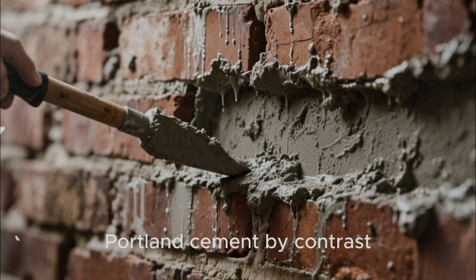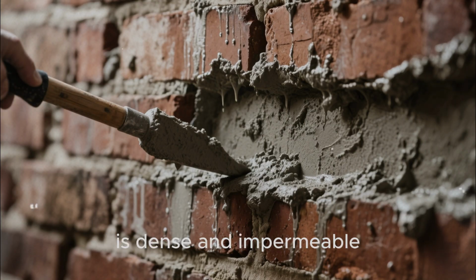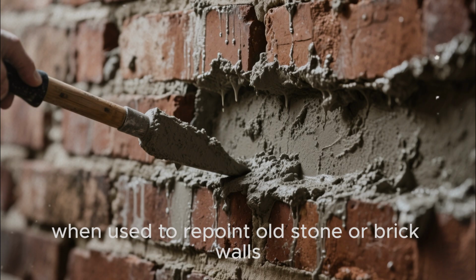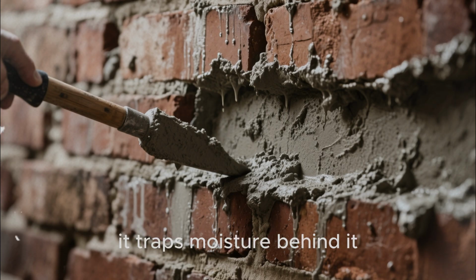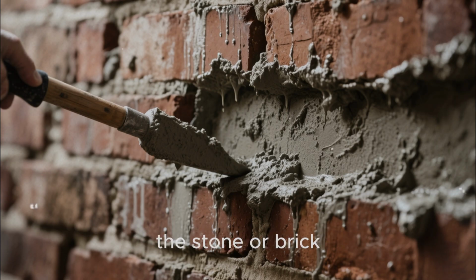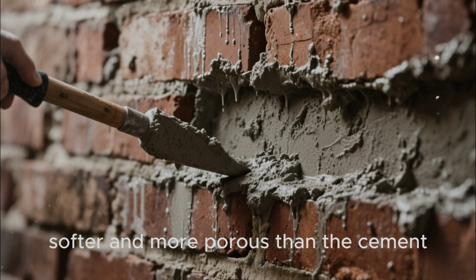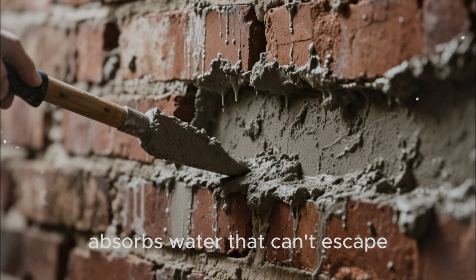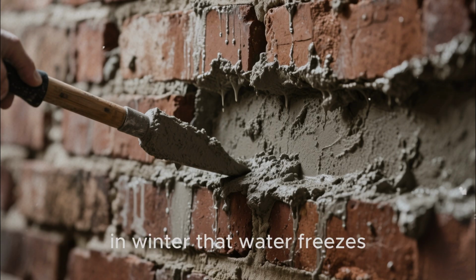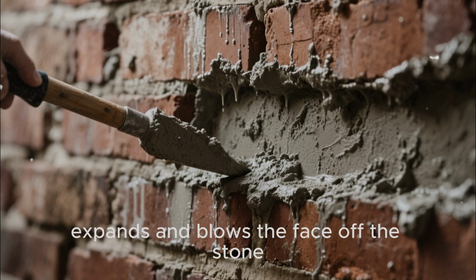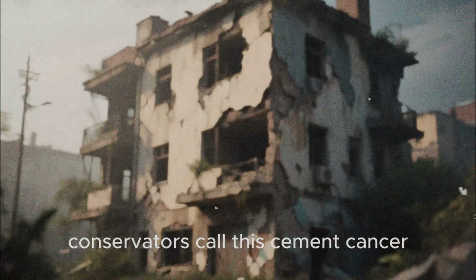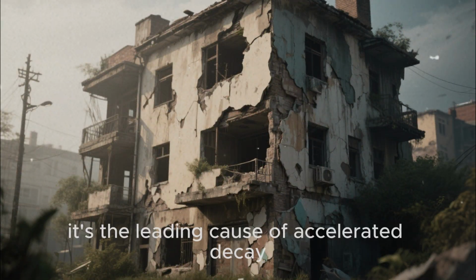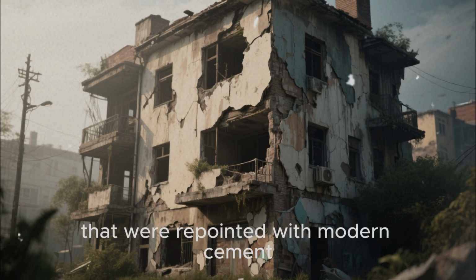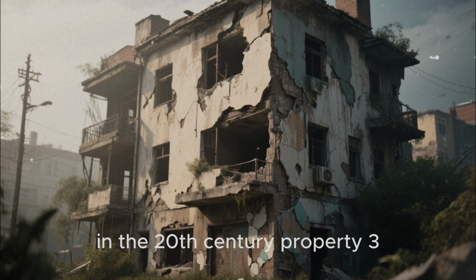Portland cement, by contrast, is dense and impermeable. When used to repoint old stone or brick walls, it traps moisture behind it. The stone or brick, softer and more porous than the cement, absorbs water that can't escape. In winter, that water freezes, expands, and blows the face off the stone. Conservators call this cement cancer. It's the leading cause of accelerated decay in historic buildings that were repointed with modern cement in the 20th century.